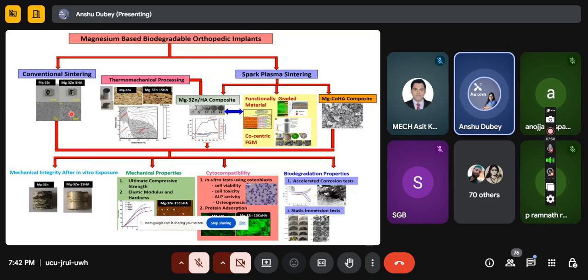We tried to develop the composites through two methods. One is conventional sintering, and the other is spark plasma sintering. In conventional sintering, we chose two compositions, one without hydroxyapatite and the other with 5% hydroxyapatite. We developed the composite using 3 weight % of zinc and hydroxyapatite. Why zinc? Because zinc is a biocompatible material, and only 3% was used because 3% is the limiting solubility of zinc in magnesium. Beyond 3%, it will lead to the formation of intermetallic compounds, which was not good for us.